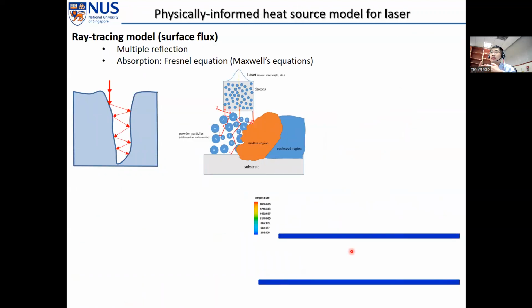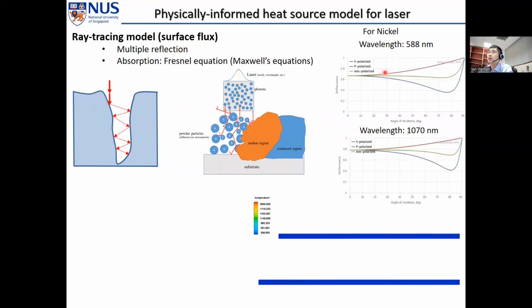And for laser, the heat source will be totally different, because for laser there will be multiple reflection, because energy absorption for each interaction is much lower. So we consider this heat source model using the ray-tracing method to track the multiple reflection. And for each reflection, the energy absorptivity is calculated based on the Fresnel equation, which is essentially from the Maxwell equation. You can see we can consider the energy absorptivity for different materials with different wavelengths and polarization. And also the influence of incident angle is also considered.